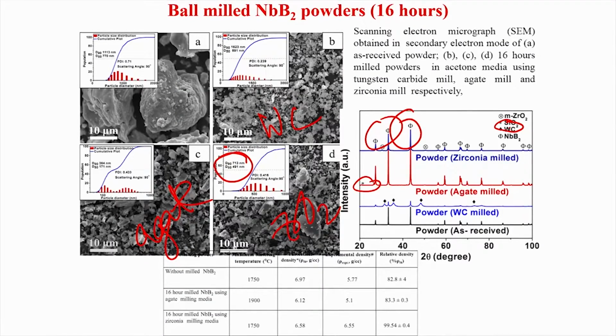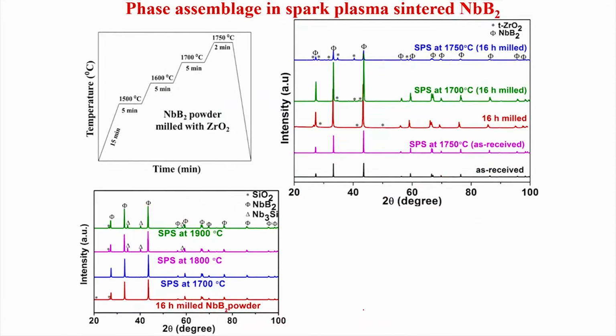Now, as far as sintering and densification is concerned, at 1750 degrees Celsius, niobium boride after spark plasma sintering is sintered to 99.5% sintered density. Spark plasma sintering is a technique very similar to hot pressing, but the fundamental difference is that current passes from the top die to the bottom die through the graphite die punch assembly, which contains these ceramic powders.